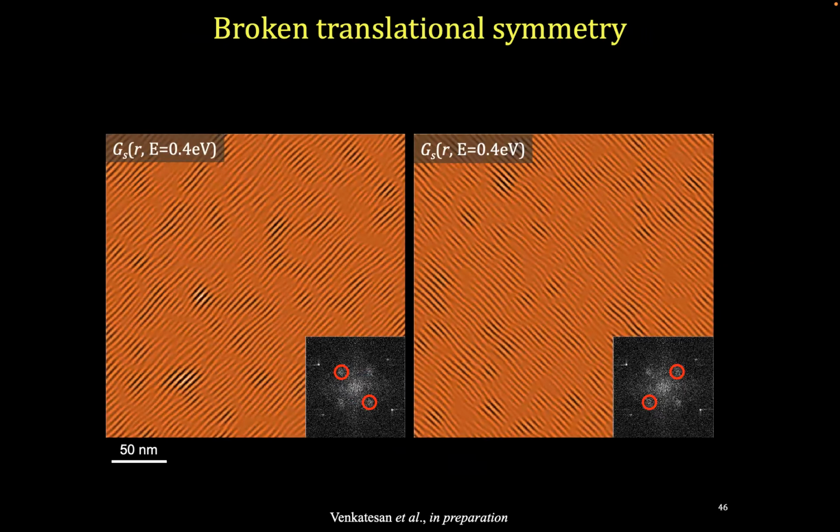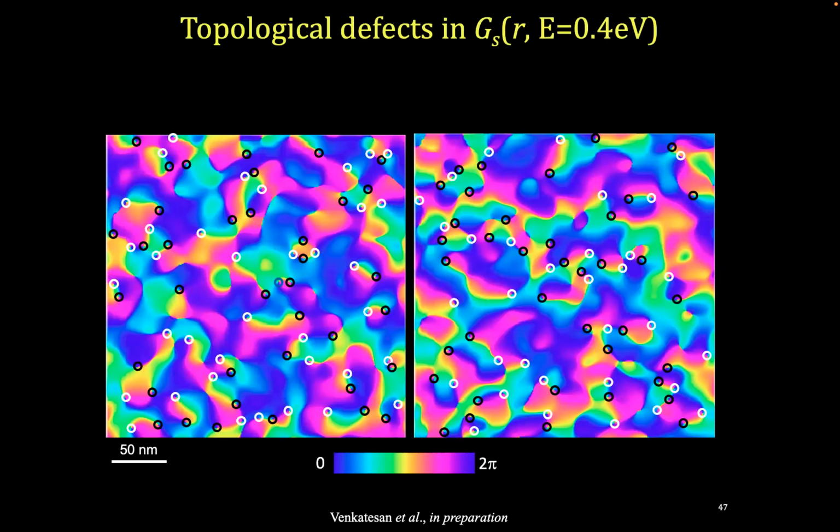So first of all, if you perform the inverse Fourier transform, you get this real space image. But to get the local phase information, what you have to do is do the local Fourier transform around this area, for example with a smaller window. And you will get the amplitude as well as the phase. Then you calculate the phase of this complex result, and that gives you the local phase. We do this at each pixel, and then you will get this particular result.